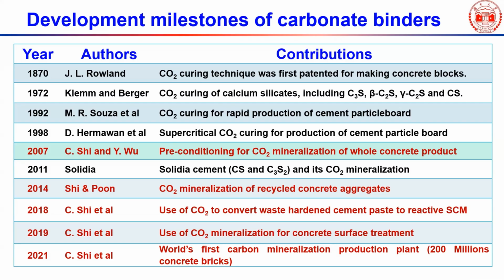But on the other hand, they found that although the surface of the concrete can react with CO2 very quickly, the reactions happen mainly at the surface and cannot go inside. So then in 2007, we published our first paper with our results.